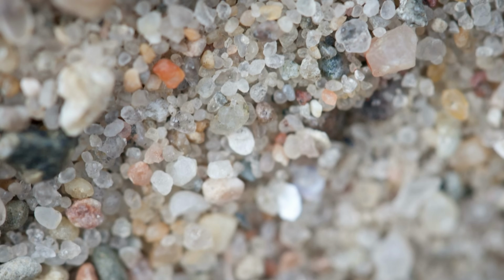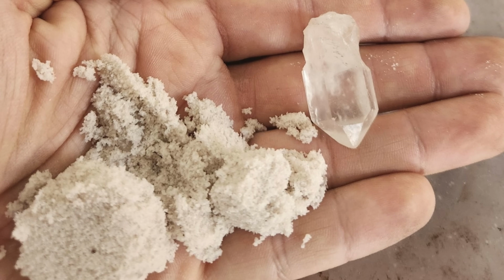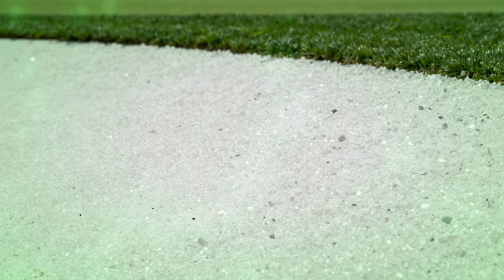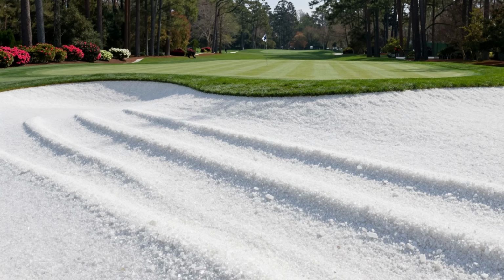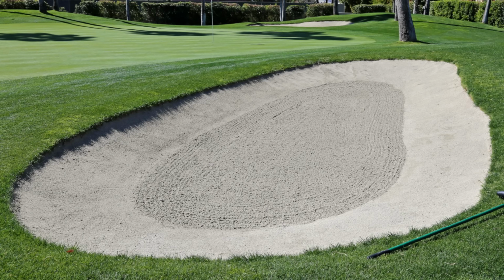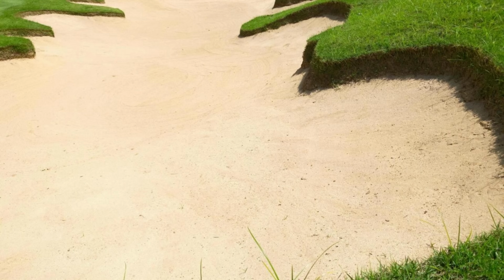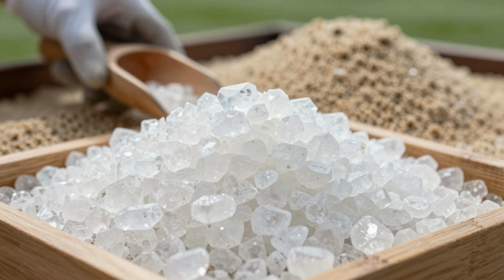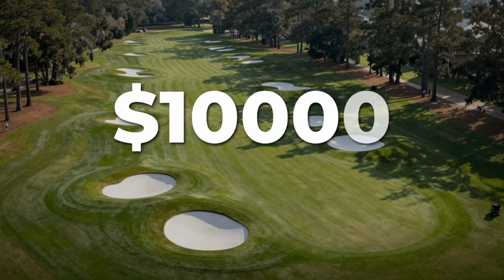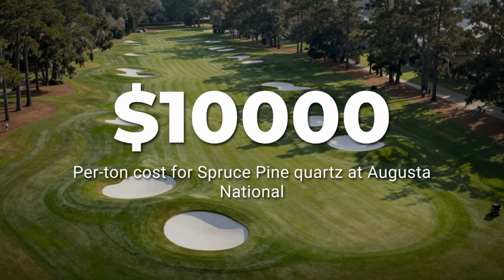The sand that isn't quite pure enough for chips, the material with slightly more impurities, still orders of magnitude purer than anything else on Earth, goes to golf courses. Augusta gets the best of the rejects. Your course, if it uses white quartz at all, gets something further down the purity chain. Regular bunker sand costs $12 to $30 per ton plus trucking. A better club might pay $100 per ton for silica-based white sand. Augusta's spruce pine quartz has been reported at up to $10,000 per ton, 500 times what your course pays.